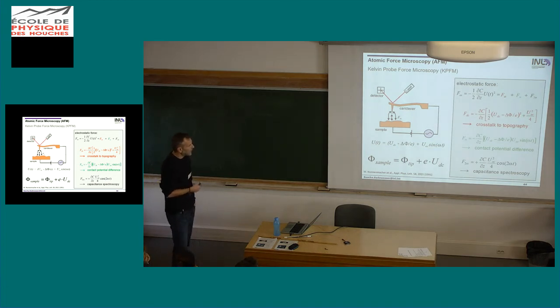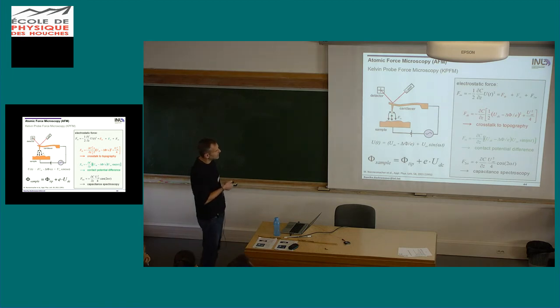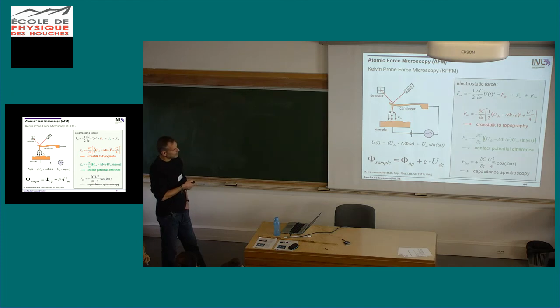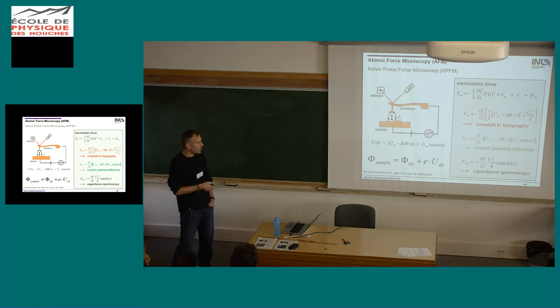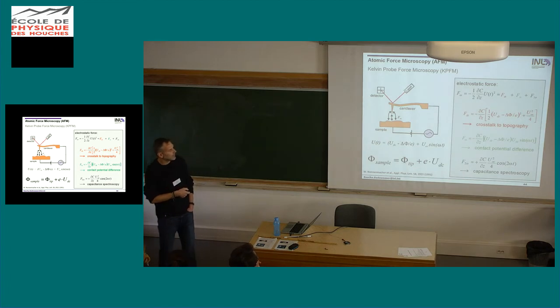So we can calculate this assuming that this is a capacitor. It's a strangely shaped capacitor, but that doesn't matter. This strange shape goes into this DC dz. And then the electrostatic force between tip and sample is written here. We just take the voltage squared. So if we plug this in, we get three terms. One is a DC term. One is a term that is the force at the frequency of the AC bias that we apply. And one is a force at double that frequency. This is just by taking out the mathematics, the square.